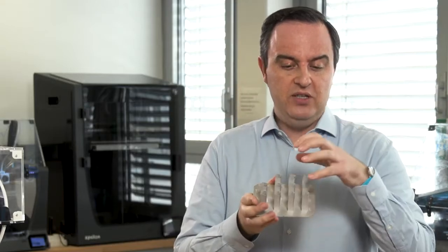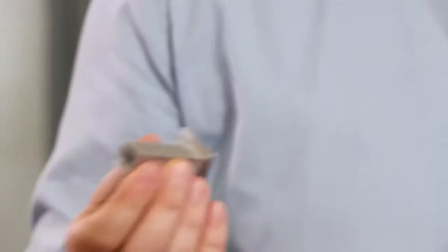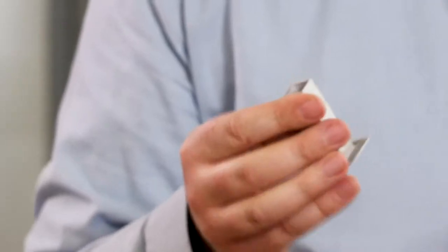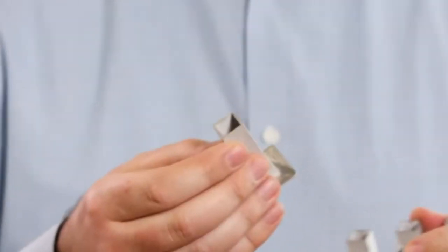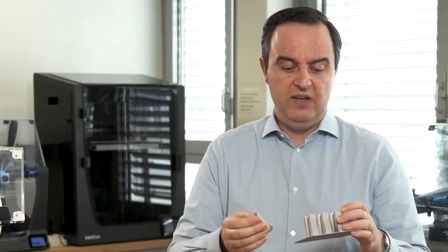These were printed and looked fine. Out of the oven, we made this so we could show how it could distort during the heat. Now, by changing our printing conditions, by matching the extrusion width and the amount of outlines to it, we're able to remove that effect and therefore show how to prevent this kind of distortion in debinding and sintering.